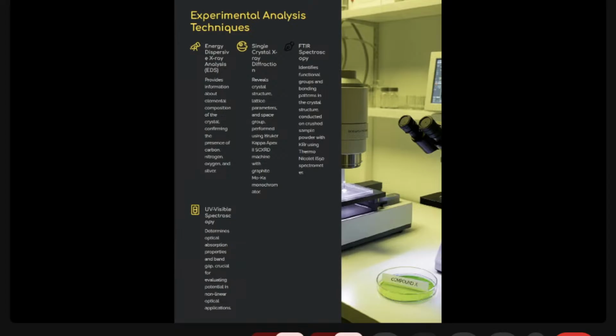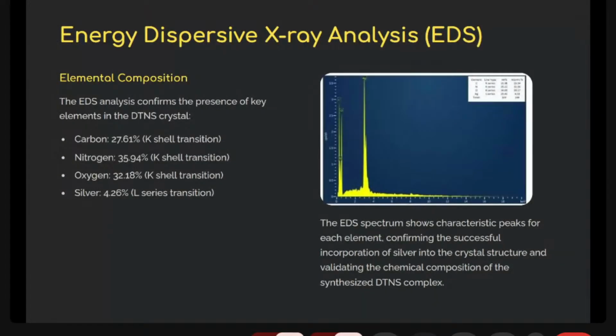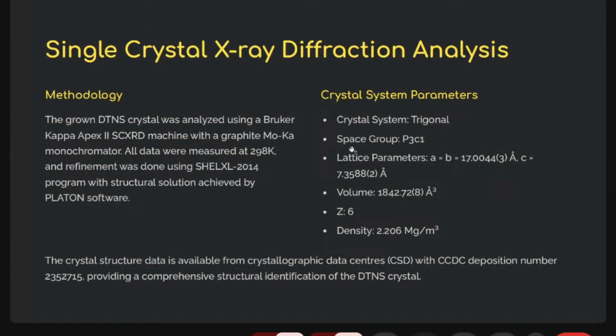Now we got to the experimental analysis. We got EDS, then single crystal XRD, FTIR spectroscopy, and then we did UV-visible spectroscopy. First of all, we did EDS because we want to know the elemental composition. Here we got carbon 27.61%, nitrogen 35.94%, oxygen 32.18%, and silver 4.26%. As you can see in the figure also, the peaks are related to the elemental composition. Now let us go to the single crystal XRD.